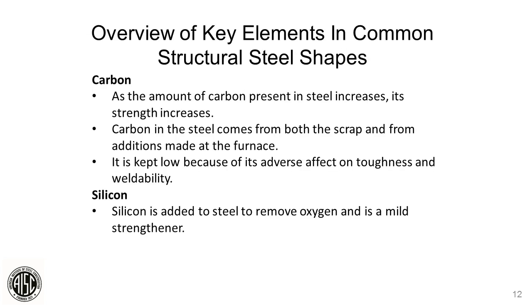So a little bit of an overview of the key elements that impact the properties of structural steel. As the amount of carbon present in steel increases, of course the steel increases in strength, but you also lose ductility and somewhat lose your toughness as well. Carbon in steel comes from both the scrap and from coke additions we put in the furnace and the Ladle Metallurgical Furnace. Primarily we keep it low because of its adverse effect on toughness and weldability. And we'll explain that in more detail.